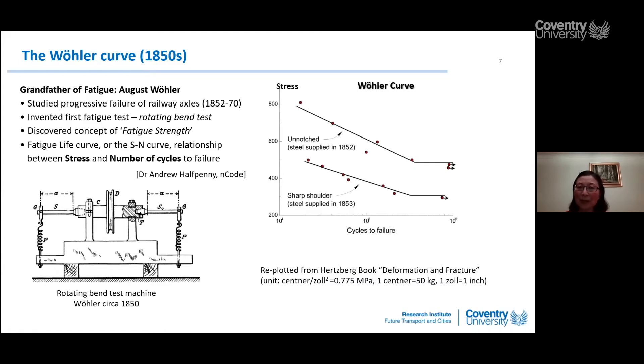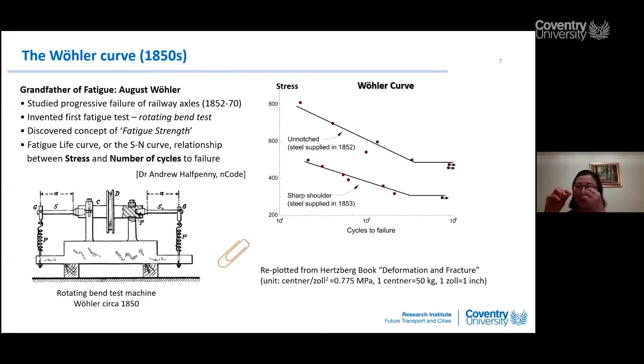The Wöhler curve shows applied stress versus number of cycles to failure. As stress decreases, fatigue life becomes longer. You can demonstrate this yourself with a paper clip — bend it cyclically and it will fail by fatigue during a lecture, even though a single static bend would not break it, as it is a ductile material.